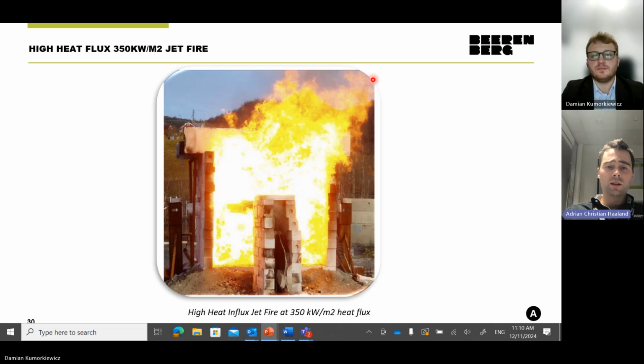As a result of this, you get heat flux up to typically around 350 kilowatt per square meter. But bear in mind that both for the standard jet fire test and for the high heat flux jet fire test, the heat flux will vary a lot. It's oscillating violently. It's not like a furnace test where you have a stable 1100 degrees throughout the test.